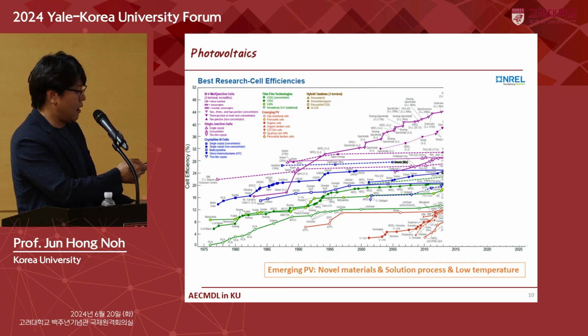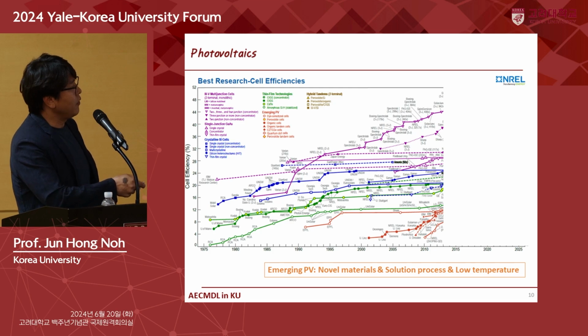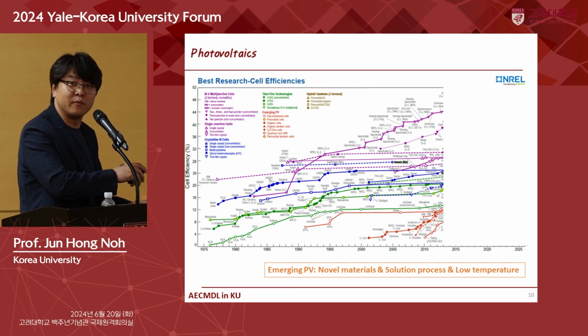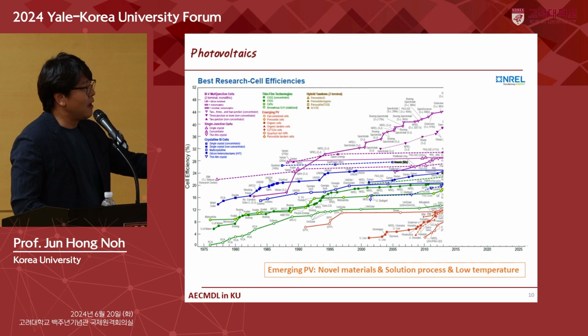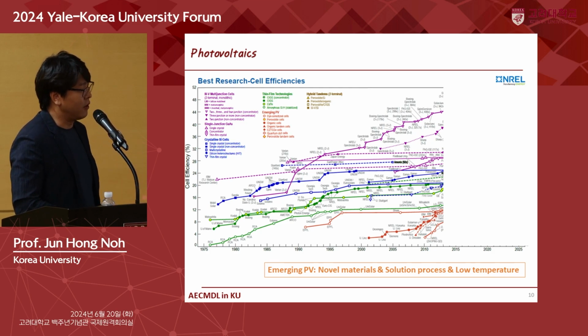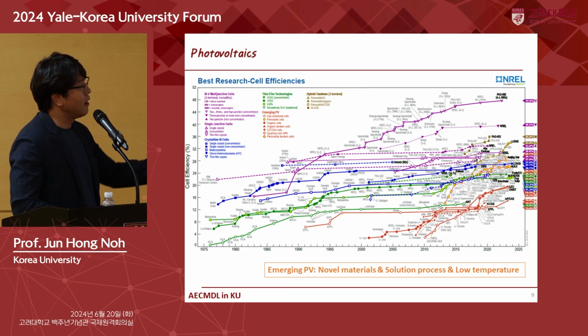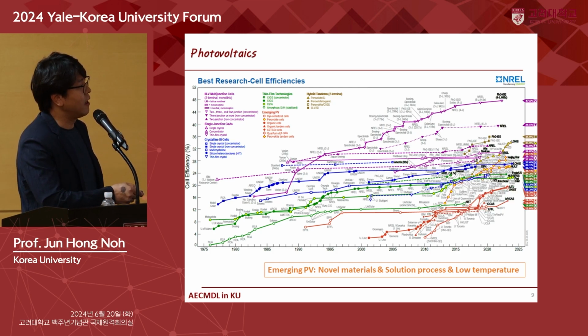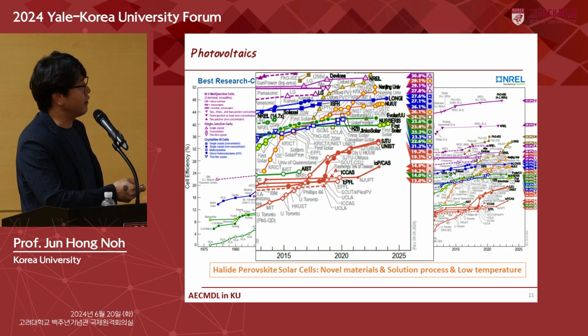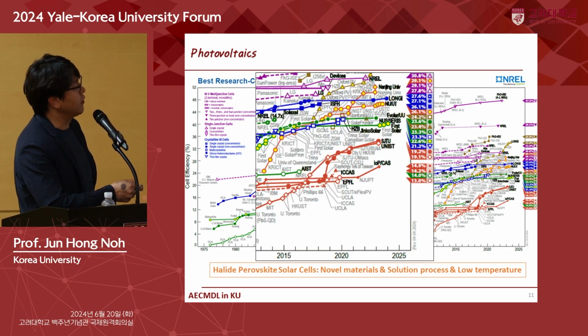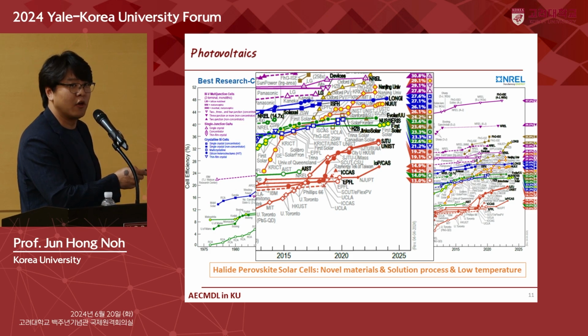Here is this red line. When you return to 10 years ago, as you can see here, the emerging PV is located at the bottom of this chart. That means the efficiency is very low compared to its potential for printing solar cells. But this time, halide perovskite has made the red line go up to silicon. I will get into the detail here. You can see perovskite solar cells emerged at 14% here, and then a truly remarkable increase in efficiency. And this time the single junction efficiency of 26% is comparable to silicon.